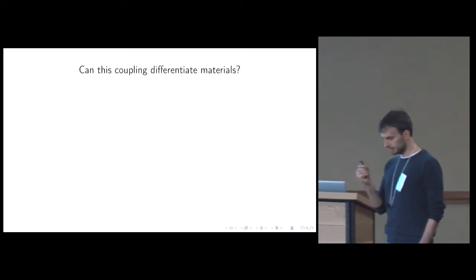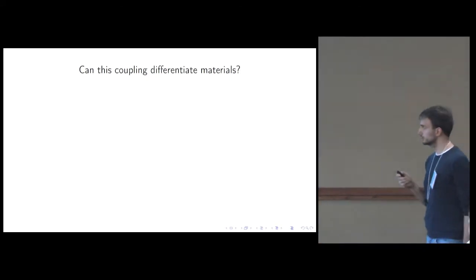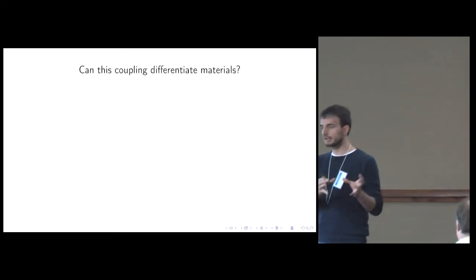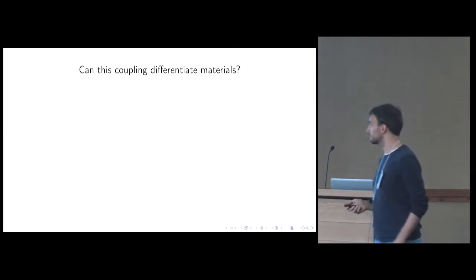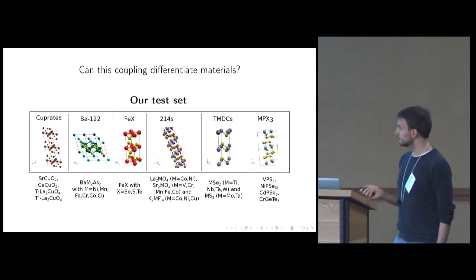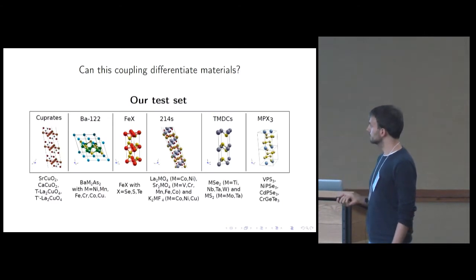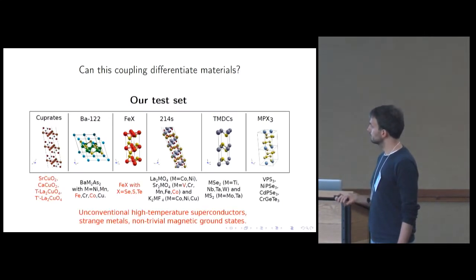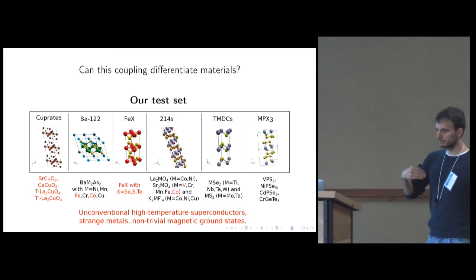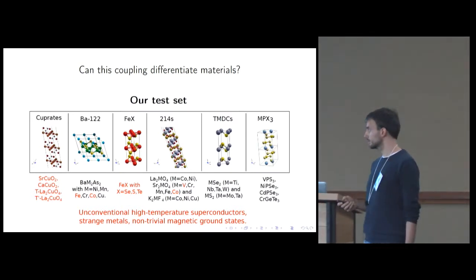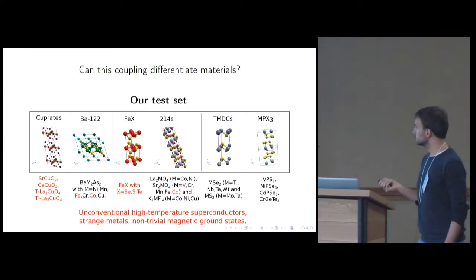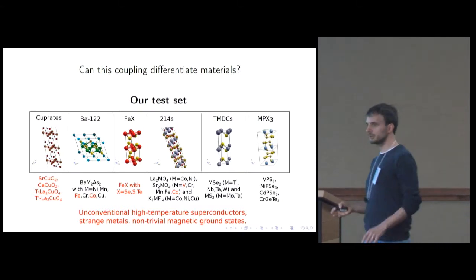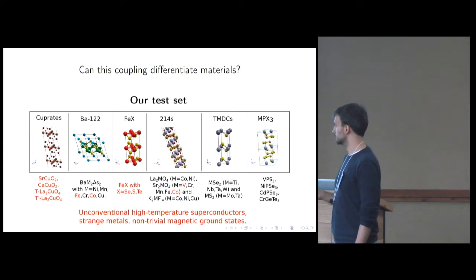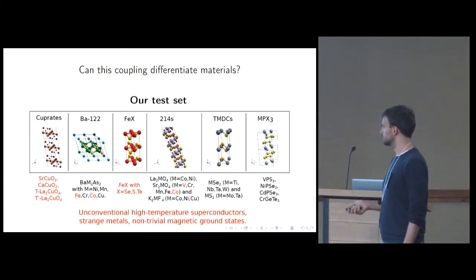The question is, can this coupling, this charge spin susceptibility, distinguish different materials, the ones that have this interesting kind of physics from the ones that have the usual, less interesting physics? In order to test that, we looked at a set of 35 materials. Some of them have interesting electronic phases, like these here that are superconducting and have strange metal behavior, where electrons flow across the material in weird ways. They have non-trivial magnetic states. Most others have the typical behavior; they don't have these unusual phases.